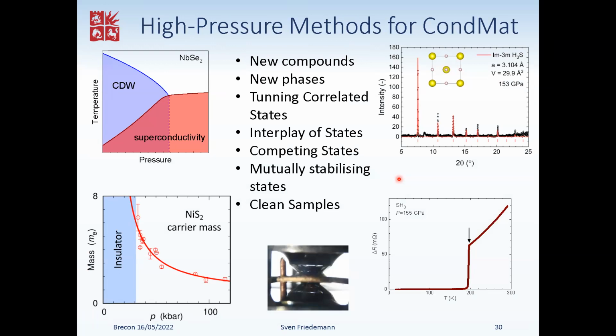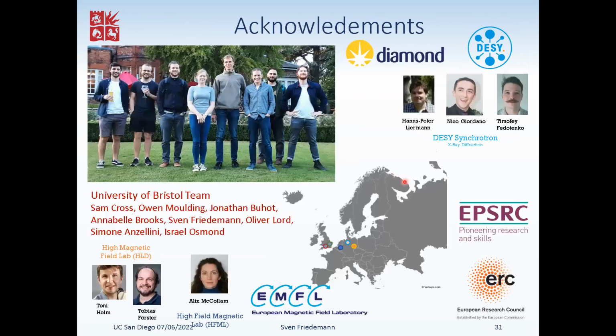We can look at the interplay of states like I've done yesterday, niobium diselenide, or competing states or mutually stabilizing states like in the elemental sulfur. And most importantly, we can put clean samples in our cells and maintain their cleanness, at least for nickel disulfide. H3S seems to be quite clean. Lanthanum H10, I've made the case, is a bit more tricky, but that's the synthesis in the first place that's tricky.